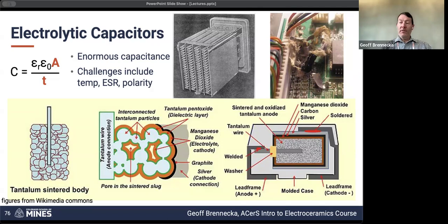And so when you make or use these electrolytic capacitors, you're going to be limited in the voltage that you can apply in the negative polarity. So I'm defining a negative and positive in this direction by what is growing the oxide layer versus what is shrinking the oxide layer. And so that doesn't mean you can't operate them in an AC manner, but it does mean that you don't want to go overboard in the negative direction, because you can drive the reaction backwards, evolve oxygen.